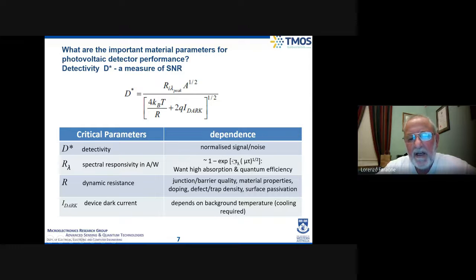This is the absorption coefficient of the semiconductor material in terms of how efficiently it absorbs the infrared photons. So obviously you want a high absorption coefficient. And it's also got this parameter mu tau, which is the mobility times the lifetime, square root of. So in order to get a high responsivity, you want a high mobility and a long lifetime.